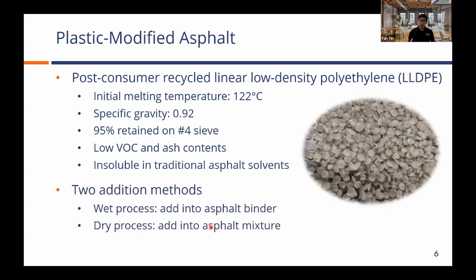The way we introduce the material into our asphalt mixture includes two methods. One is what we call the wet process. Basically for this process, we are adding these pellets, as you can see on this screen, into the asphalt binder. Because it goes into the liquid phase, we refer to that as the wet process.